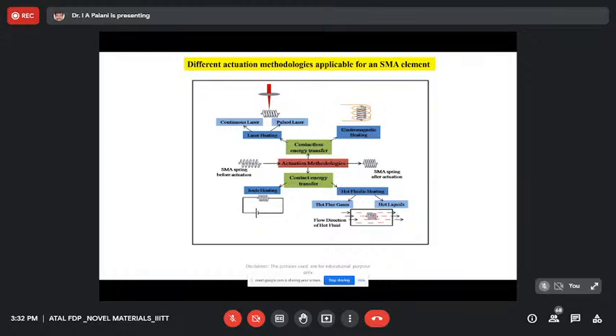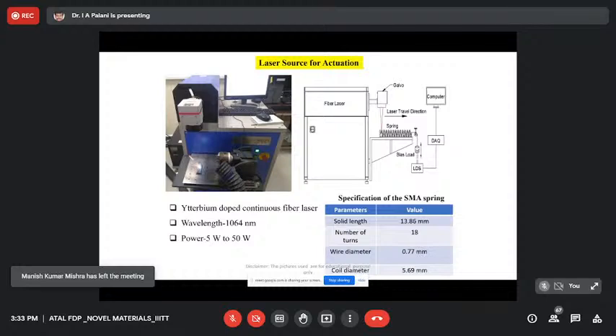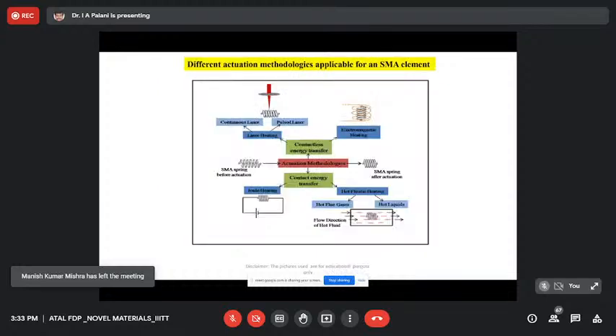So what we did is, we had a continuous laser and we had a pulse laser, and this is a kind of contactless energy transfer. So using this contactless energy transfer, we were trying to heat it, and we were trying to study the characteristics. In this contactless energy transfer, again we also used a hot water connection. So in this hot water, you keep a fluid. Inside this fluid, you're trying to heat the surface, and you can study the behavior.